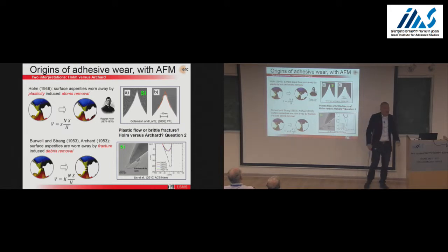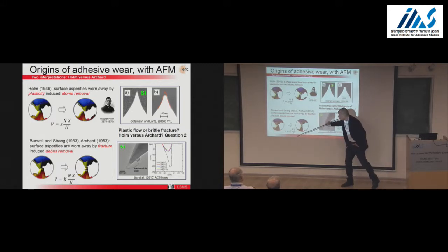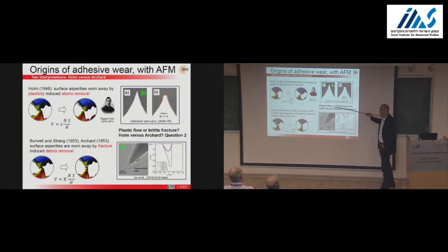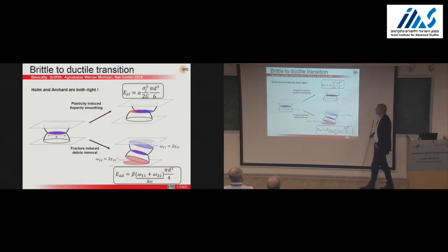Occasionally, you do find AFM data where the tip breaks, and here you see a snapshot of this, where the tip is actually stuck due to van der Waals forces on the side of your AFM tip. So occasionally, you do recover Archard description of adhesive wear. So you have those two different visions. So what do we have? What should we expect? Plastic flow, brittle fracture, Holm versus Archard? That's a second question. I will start by answering this.